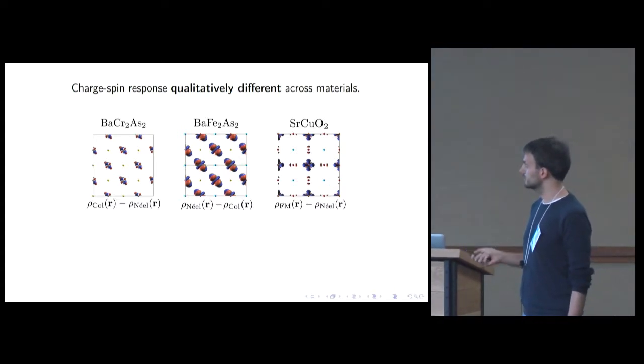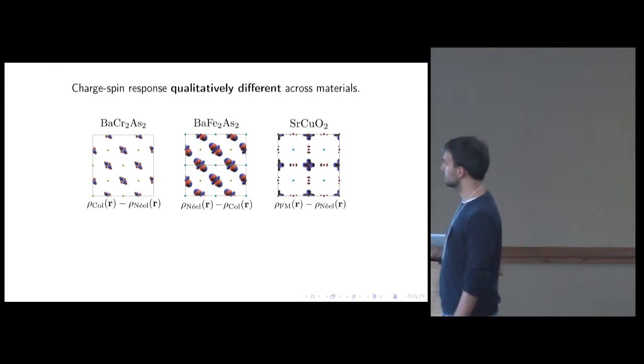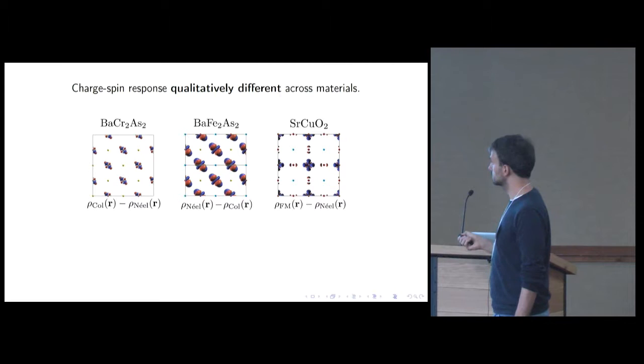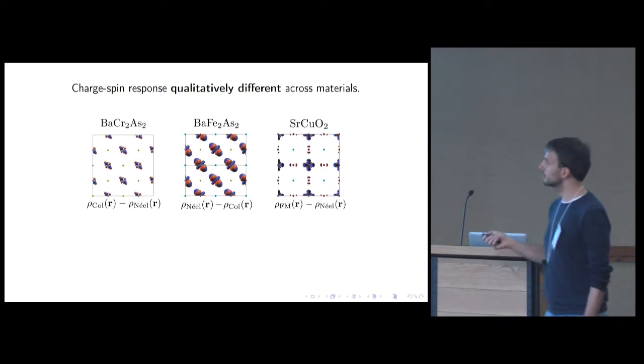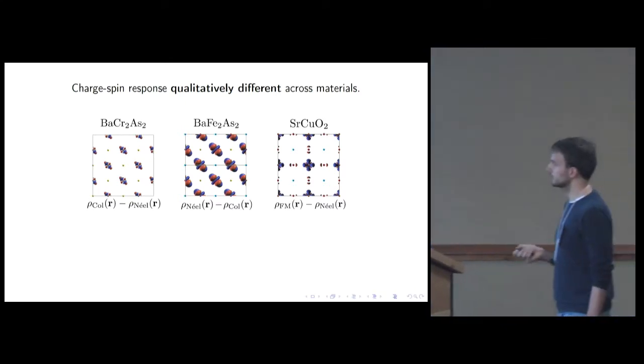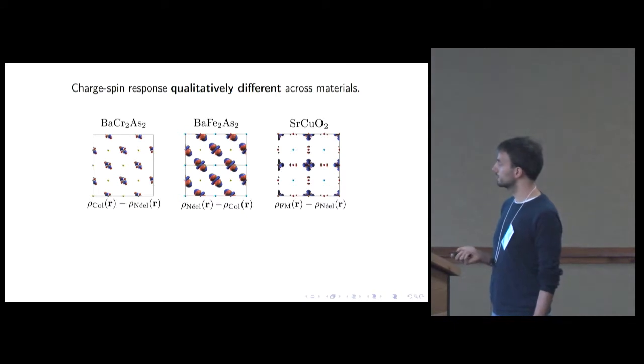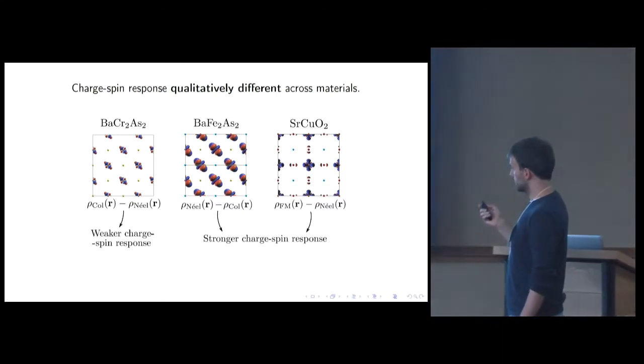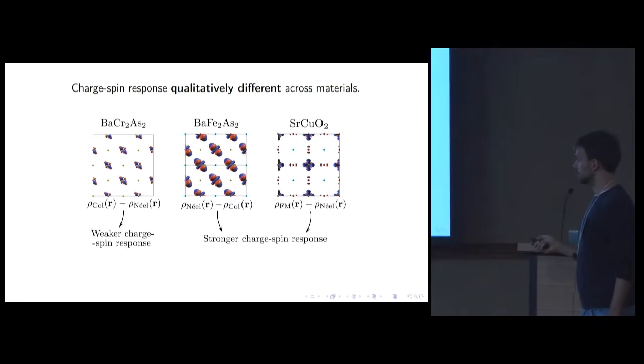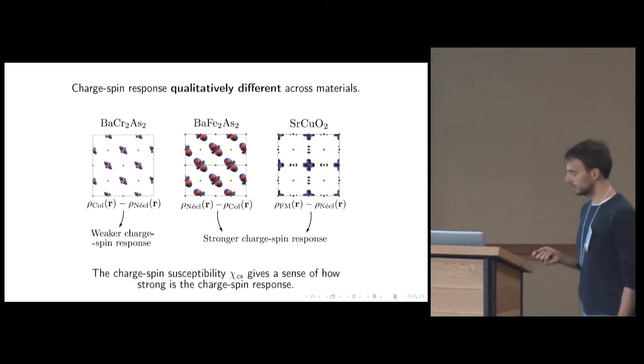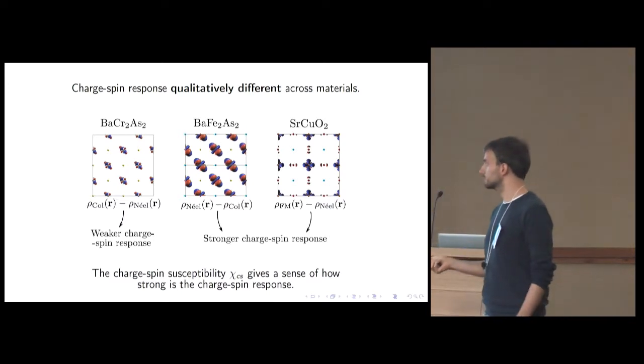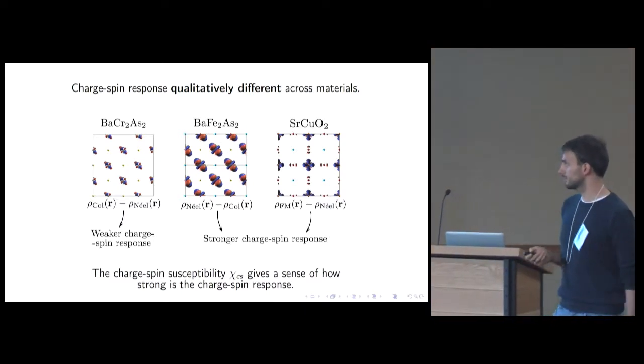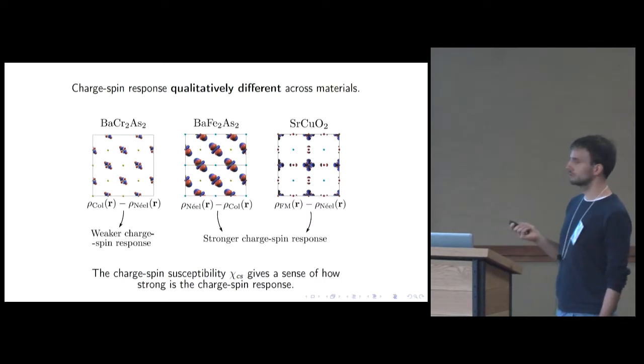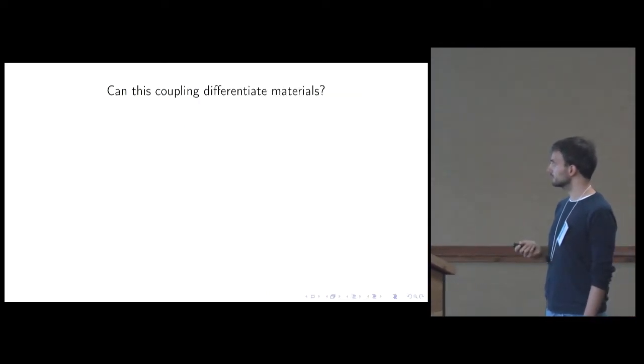This one is the one that I was just discussing. This other one is a cuprate that is known to be a high temperature superconductor also. But you see that charge rearranges very differently in this case when compared to this one. And this is an insulating magnetic material that has a much weaker response. So qualitatively, these responses are different, but the magnitude can be condensed in this charge spin susceptibility that I introduced in the previous slide. That is what we are going to be measuring in each material.